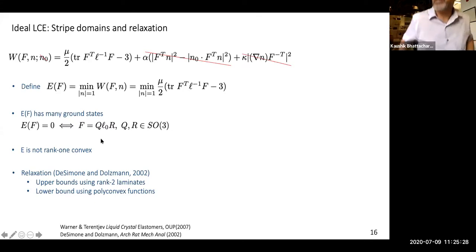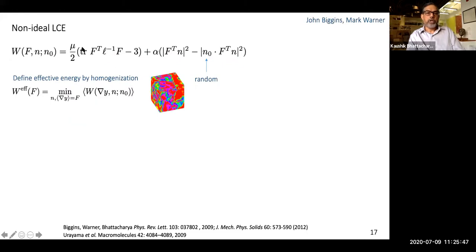So about 10, 15 years ago, the belief was you have to very carefully make the material, because in order to get the soft behavior, you had to make the non-ideal term zero. So what happens when you have a non-ideal material? I can no longer compute. Now I not only have a non-convex energy, but I also have a heterogeneous energy, because this n naught is not uniform. It's actually a fluctuation and hence random. So what you have is a material which is extremely heterogeneous.